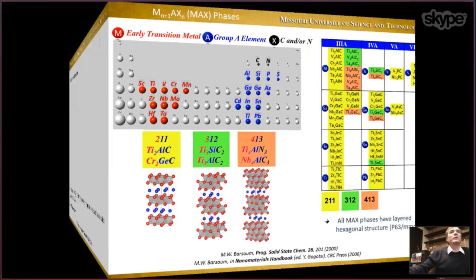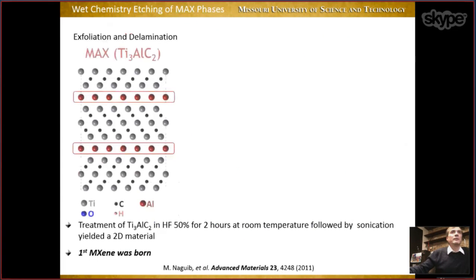Now, what do we do with those MAX phases to produce MXene? So here is an example. We take one of those MAX phases, which is Ti3AlC2. This one has MX blocks of 5 atomic layer thickness. So it's M, X, M, X, M, right? And here is the layer of aluminum, the A element, okay? So we take this MAX phase. MAX phases are well known. We did not discover them.